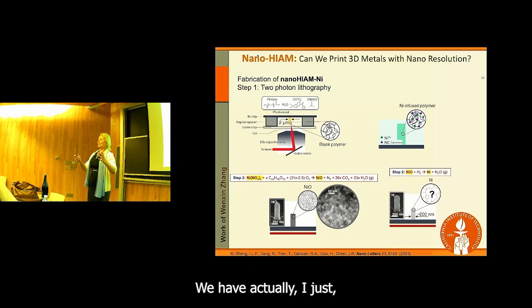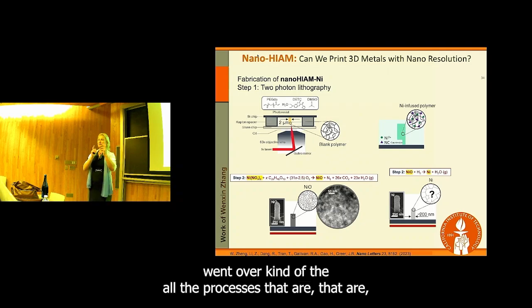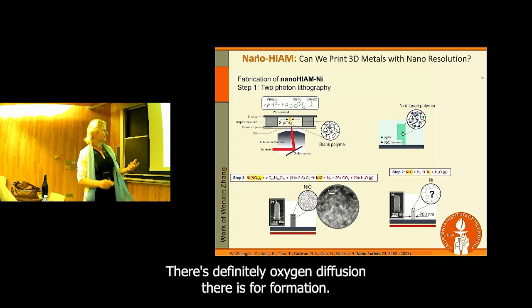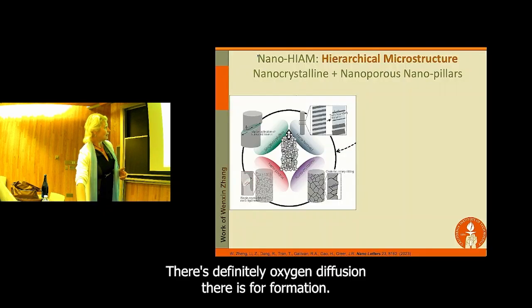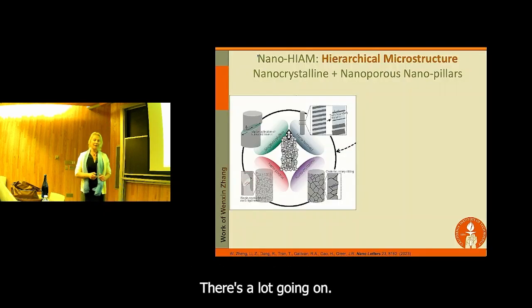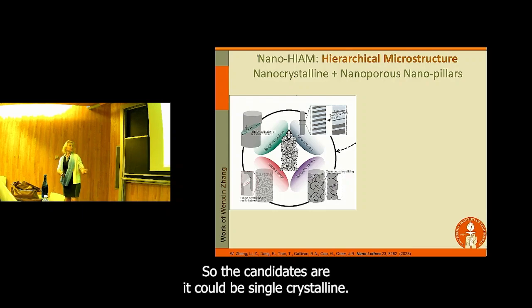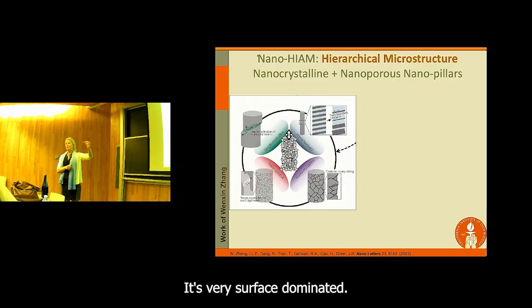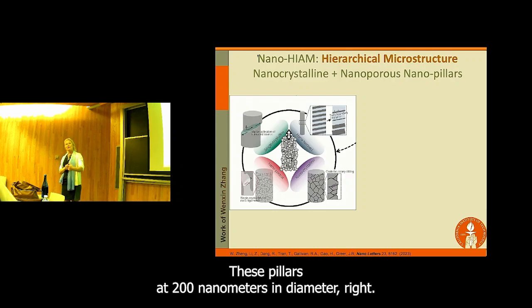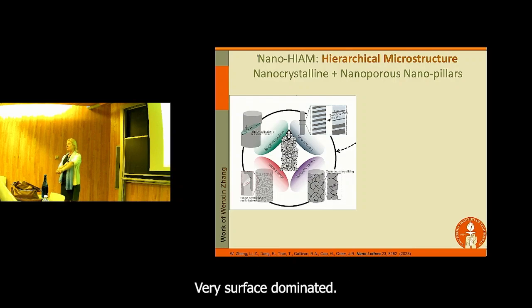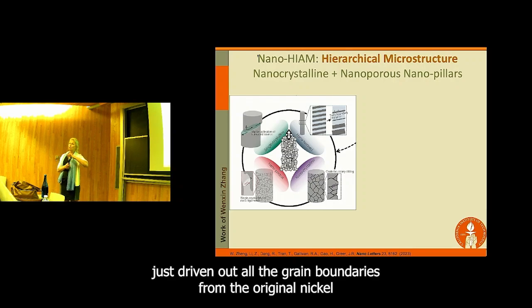I just went over all the processes that accommodate this transformation. There's definitely oxygen diffusion. There's pore formation. There's a lot going on. So the candidates: it could be single crystalline. It's very surface dominated. These pillars are 200 nanometers in diameter, so we could have just driven out all the grain boundaries from the original nickel oxide grains.